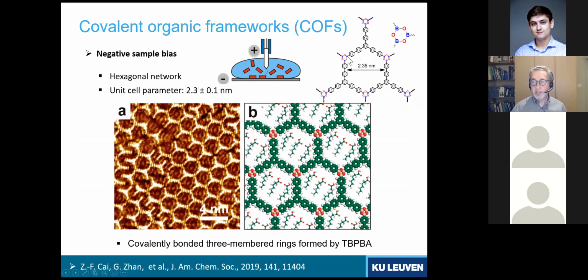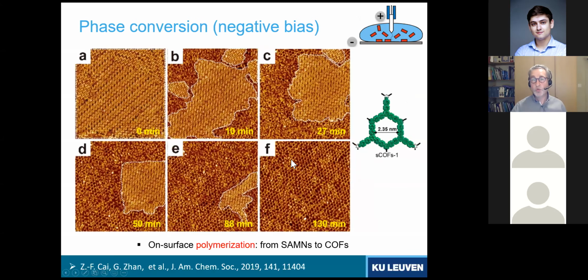in nature. By changing the bias polarity, we can actually, at room temperature and locally, induce a reaction where we create these boroxine groups and form what we call two-dimensional surface-supported covalent organic frameworks. And it's pretty cool that we can do so, because by using the STM, we can actually use it as a trigger to start locally the reaction. And therefore, it can also allow us to follow the reaction process in real time.